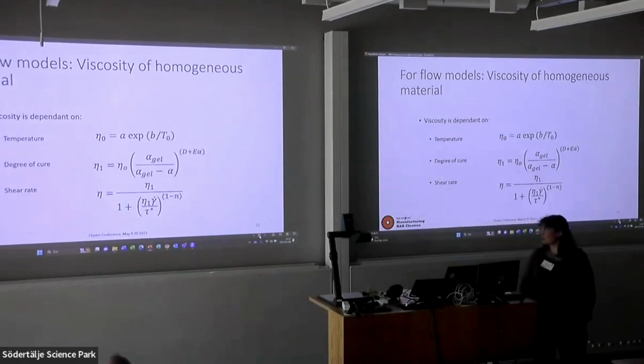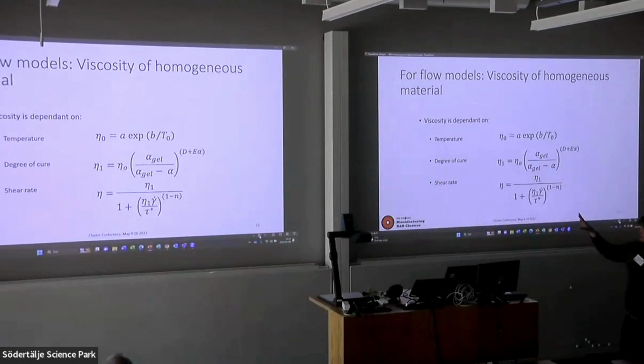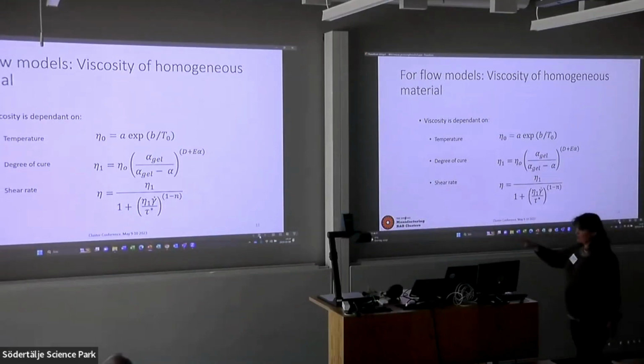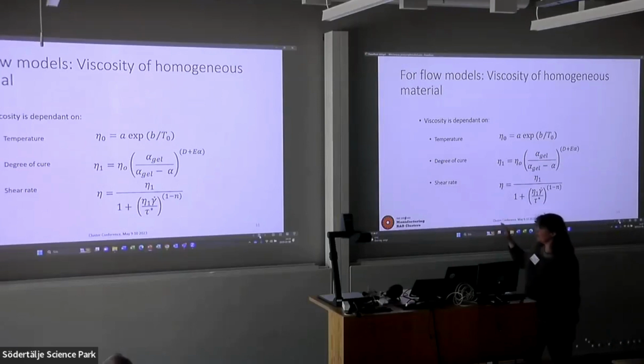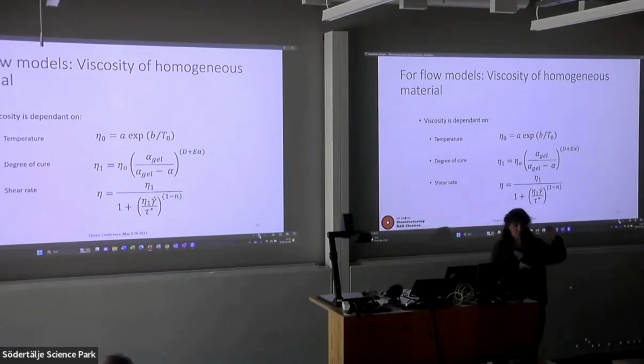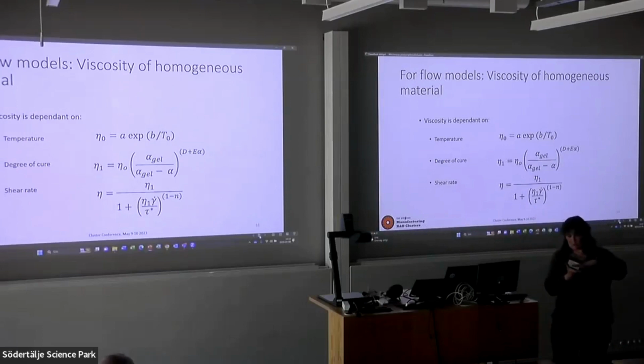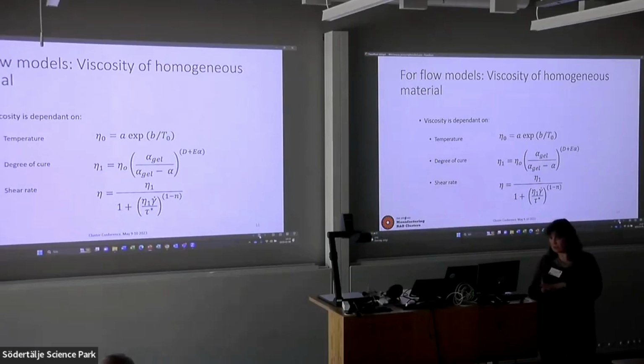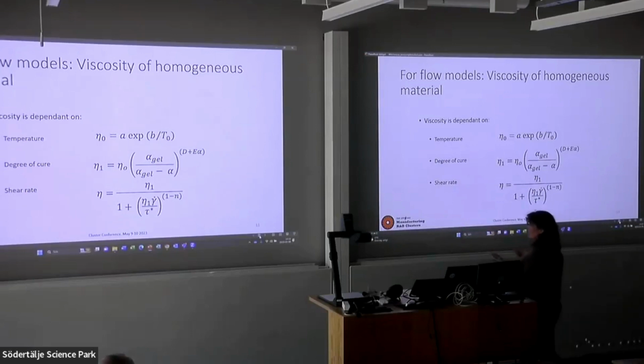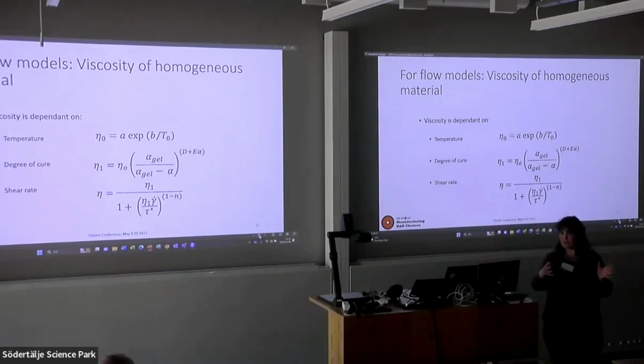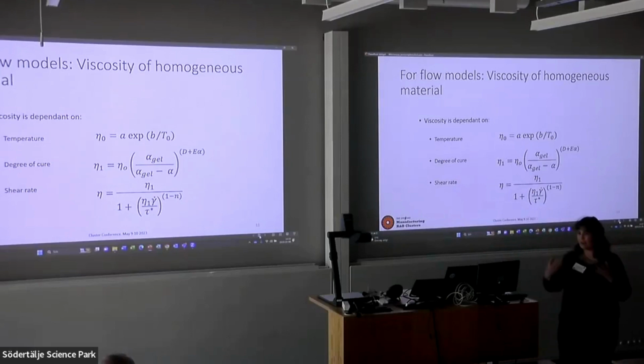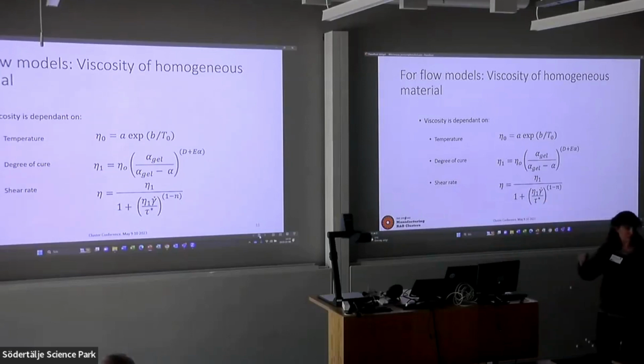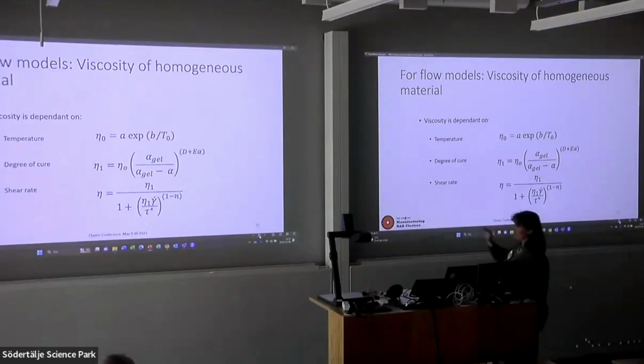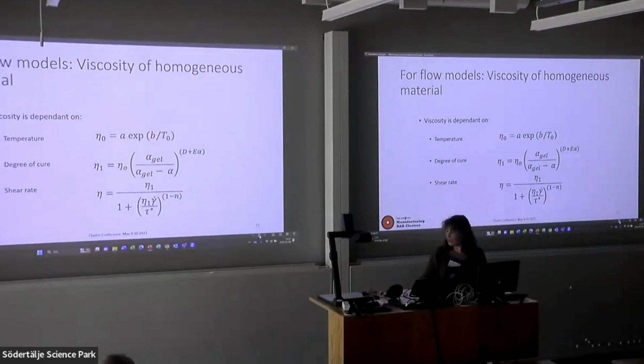So these are the models that we're using. The first one, the temperature, and the last one, the shear rate, are both important. Like I said, the degree of cure, given that you're modeling the compression stage, which is only maybe 3 or 4 seconds, we don't really have an issue with the state of cure. The cure comes in the fact that you have to lift the piece of sheet over into the tool, then you have to back off, you have to wait for the things to close, and that's when you start having problems with the cure. But it's not really something that's captured in the model itself.